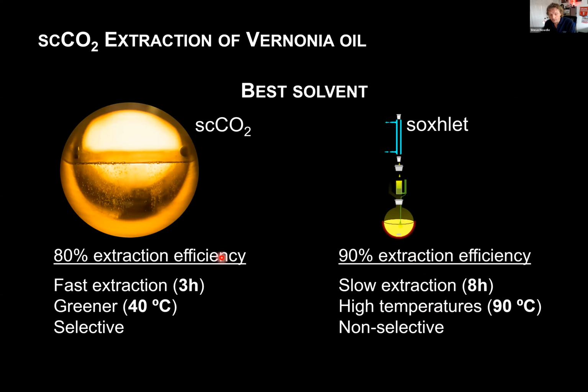In fact, CO2 is a very efficient way of doing this. It turns out that the extraction is much quicker than using the normal solvent in a Soxhlet extraction. We use much lower temperatures, and it's actually quite selective for the Vernonia oil — the other oils that are present are not extracted very effectively using CO2.